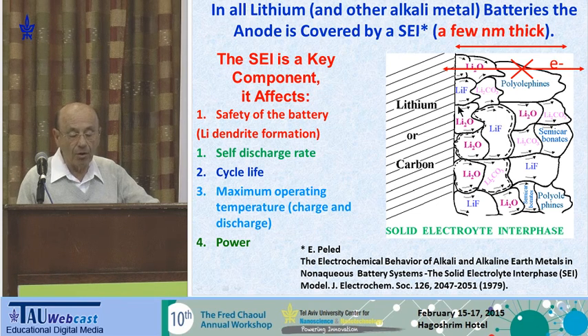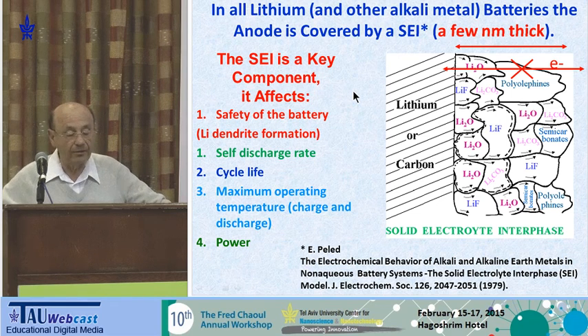Now, all these nanoparticles are cation conductors, and these conduct lithium cations. So when you charge or discharge, lithium cations go from here to here and come into the solution. Now, this is happening in all lithium and other alkali metal batteries. The anode is completely covered by SEI, a few nanometers thick. It's 2 to 5 nanometers. And if you do not design this condition, the battery is dead.